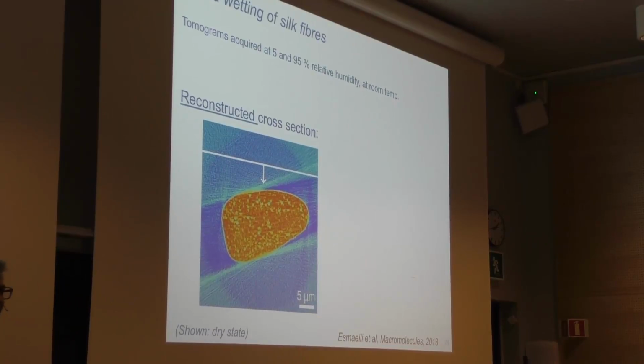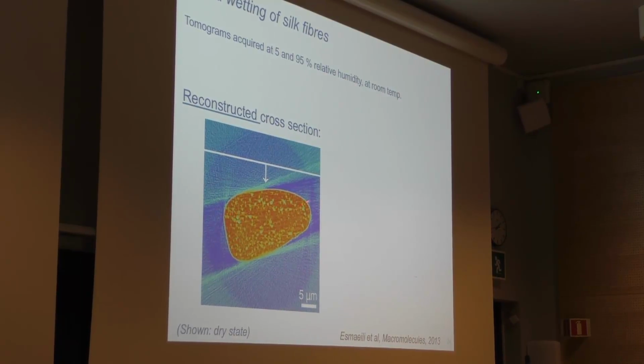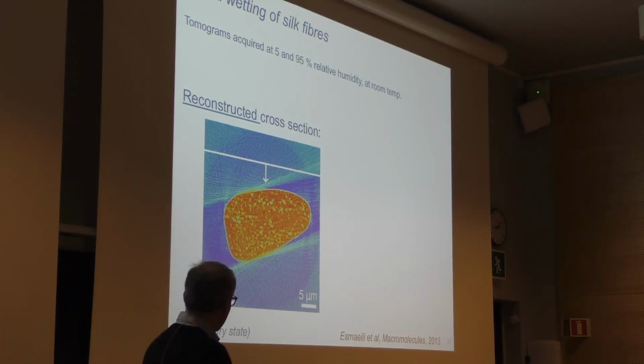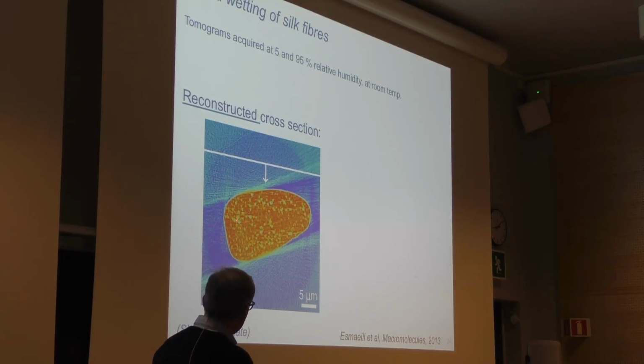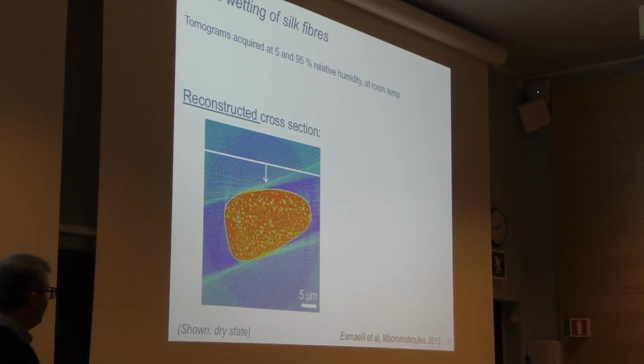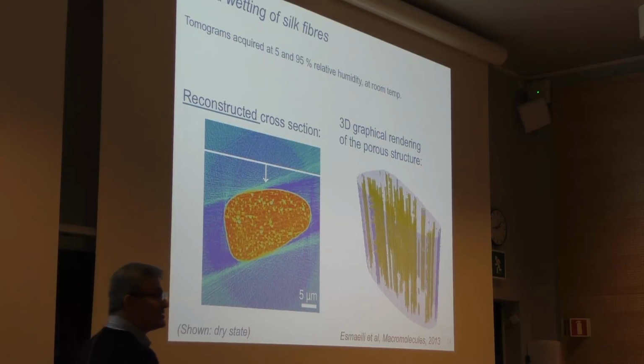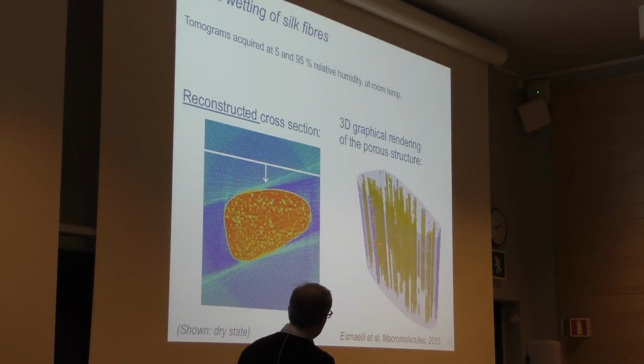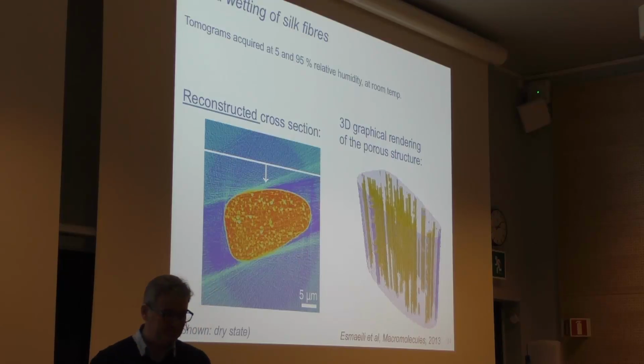So here is one example of a cross-section that we get. So this is numerically reconstructed from a range of scattering patterns. And you can see the well-known facets of silk here. And inside you can see that there are all these small features that are pores inside of the silk fiber. Another way of viewing this is shown here in 3D, where you can clearly see that these pores inside of the silk fiber are features that are running parallel to the long axis of the silk fiber, right?